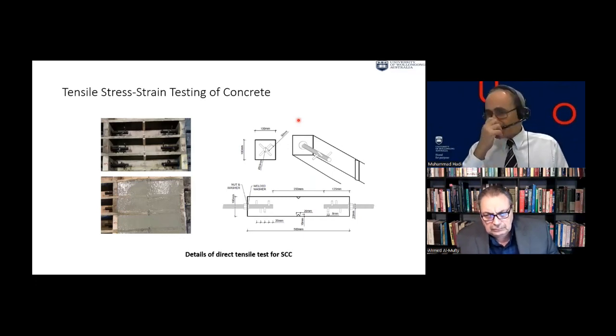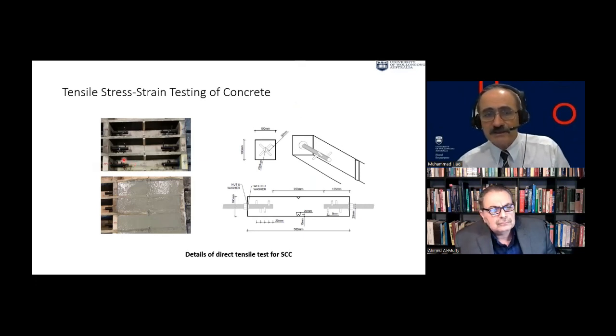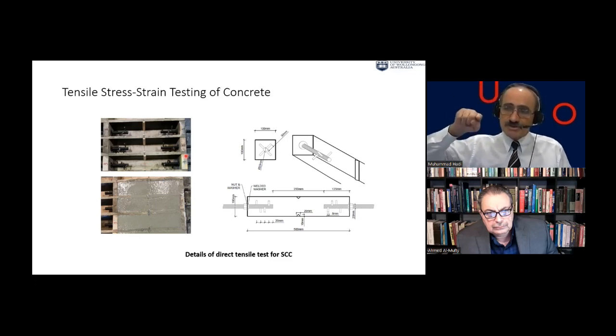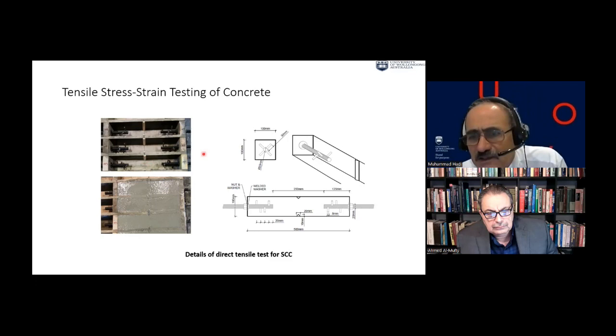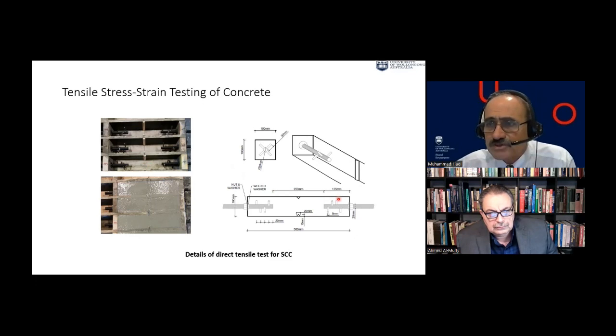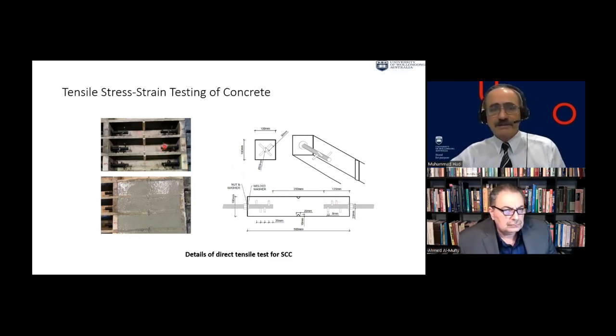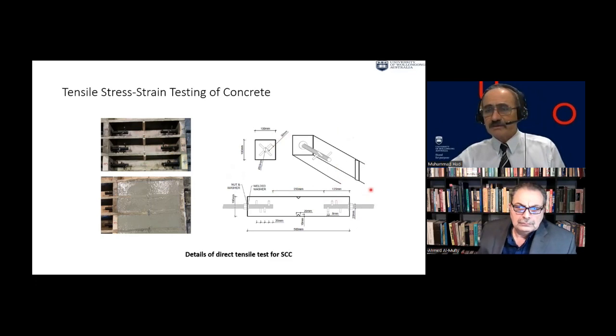And in effect, they put some bars and they welded pins on them. So this is one. And in order to ensure that the failure is in the middle, they put notches. They are 20 by 10 notches, prisms. And they put all those. And this is all the detail of the pins.